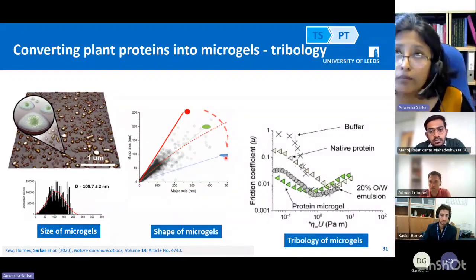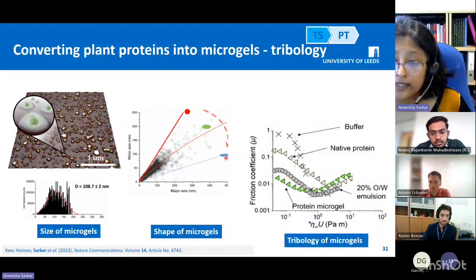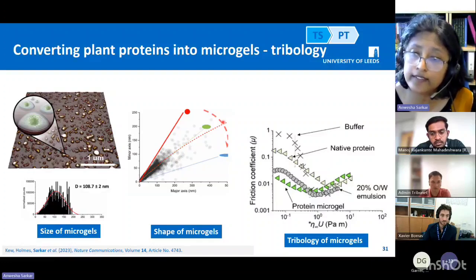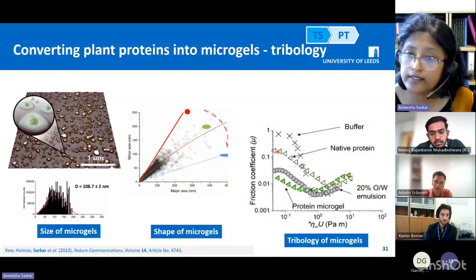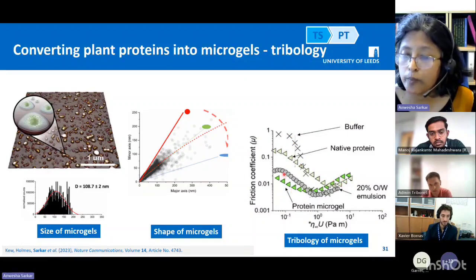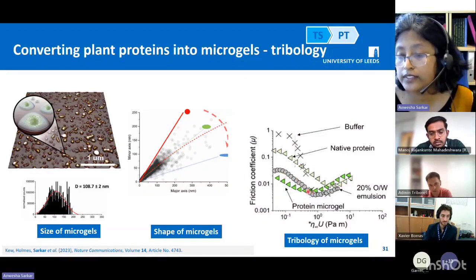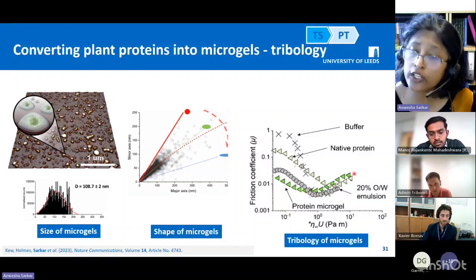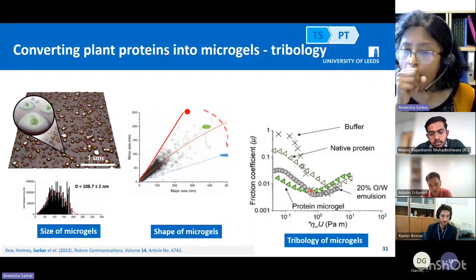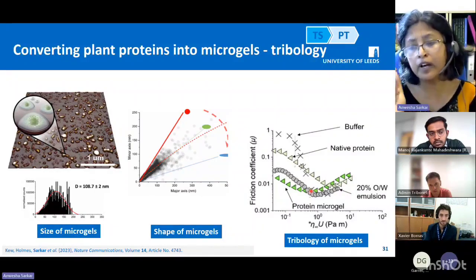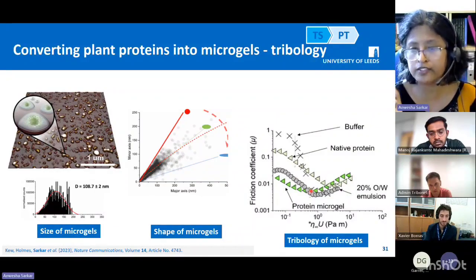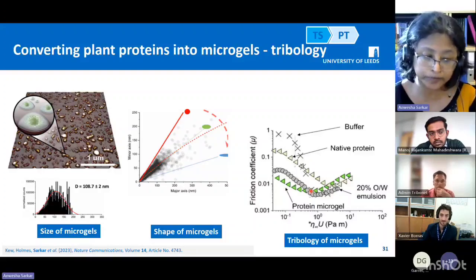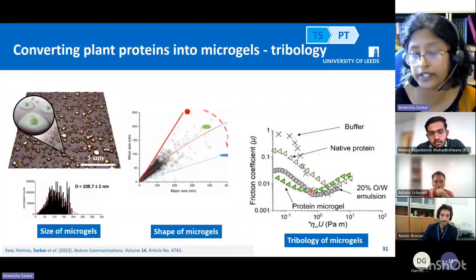And this is the most important data. What we observed is that this is a buffer, this is the native protein, and when you make a microgel, the gray one, it behaves just like an oil in water emulsion. But bear in mind, the microgel does not contain any oil. So this was pretty striking.